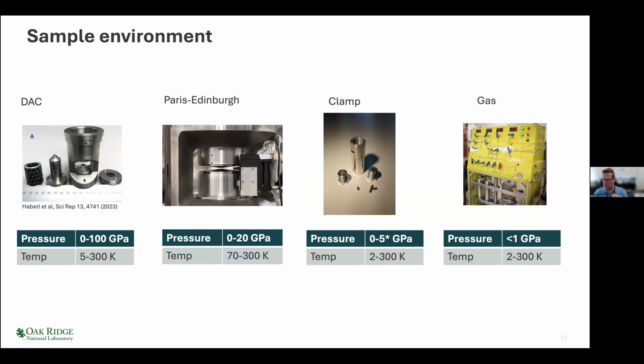This is with a massively larger volume than you can get with the diamond anvil cell. So you can do different things with that. You can even do inelastic neutron measurements with this, exploiting that larger volume. And then finally, we would have the gas cells, which are larger volume still, but for those of you who may have worked with high pressure gas, you will recognize that this is a 10 kilobar system, which we have, and is actually quite scary for high pressure gas work. And as far as I know, there are only 2 or 3 neutron facilities in the world which can operate at this higher pressure.